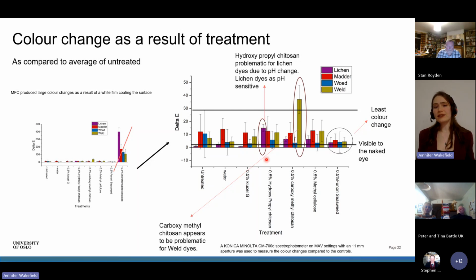And here you could clearly see a change compared to all the other lichen treatments. The hydroxypropyl chitosan produced a large color change. So that is problematic for the lichen dyes. And for the carboxymethyl chitosan, it was the yellow that produced a large color change.